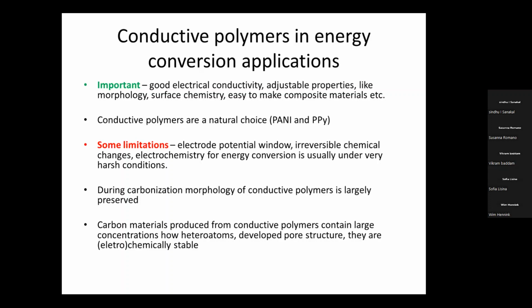Another possibility is to produce carbon materials from these conductive polymers. Of course, then we lose some good things. I mean, we lose this specific molecular structure, but carbons are generally good electrical conductors. When we derive these carbons from polyaniline and polypyrrole, they usually contain a large concentration of heteroatoms, like oxygen, which is present basically on every carbon surface at some percent.